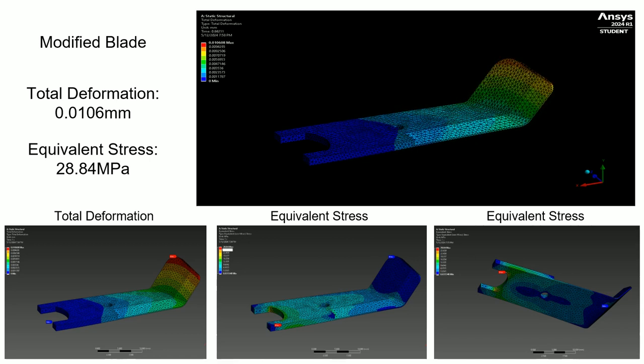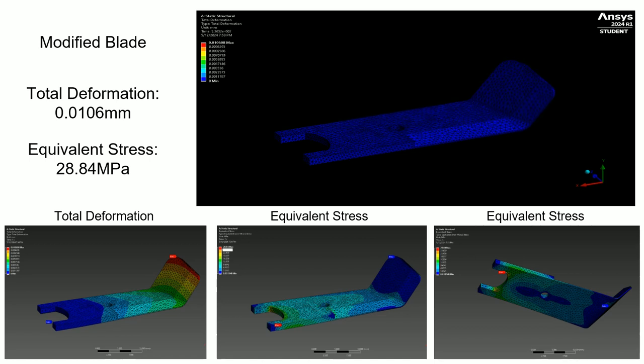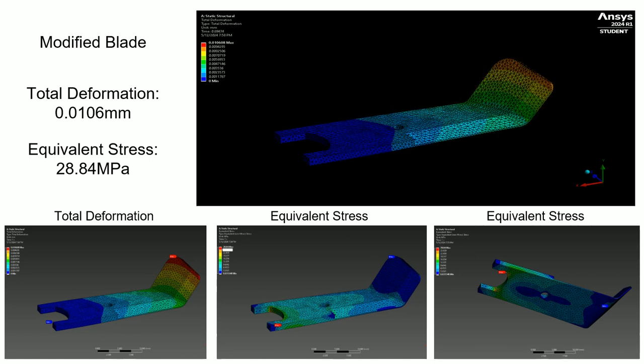The total deformation on this modified part was decreased by 53% because of the decrease in frontal area that the force was applied. The von Mises stress also decreased by 57%, which resulted in a lower stress concentration at the mating faces.